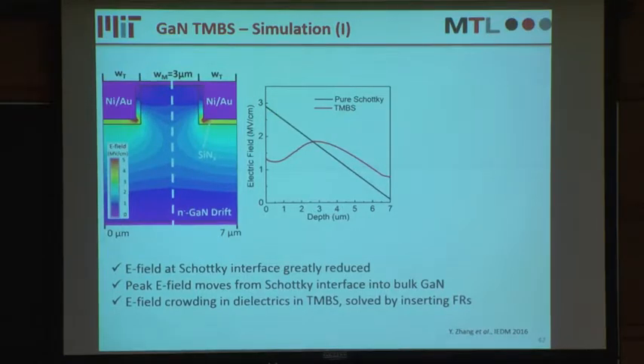In this TMBS diode, because we have this MIS barrier at the sidewalls, and this MIS barrier can have a strong depletion effect, the peak electric field can move from the surface into the bulk, and the electric field at the top surface will be greatly reduced.